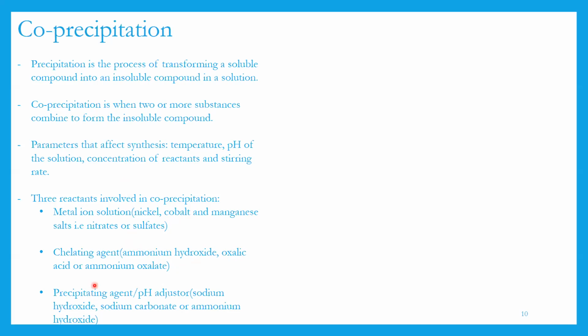Then when you apply the precipitating agent or pH adjuster and they precipitate out of solution, each particle contains the same composition of these metal ions. It's not like one will have nickel, another cobalt, another manganese. It should all be the same in each and every particle.